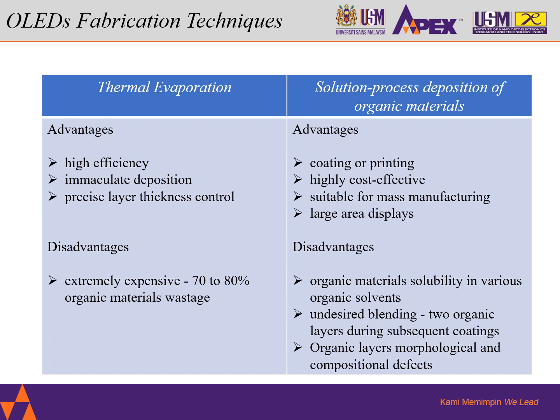OLED fabrication techniques and design challenges. There are two types of fabrication for OLEDs. The first one uses thermal evaporation, and the second one uses solution process deposition of organic materials. For the first one, thermal evaporation, there are several advantages: it can achieve high efficiency, immaculate deposition, and very precise layer thickness control. However, the disadvantage is that it is extremely expensive due to the huge wastage of the organic materials in the chamber. It is up to 80%.